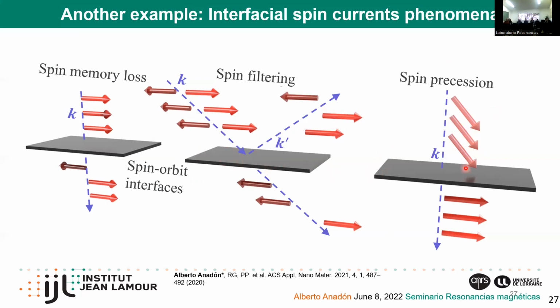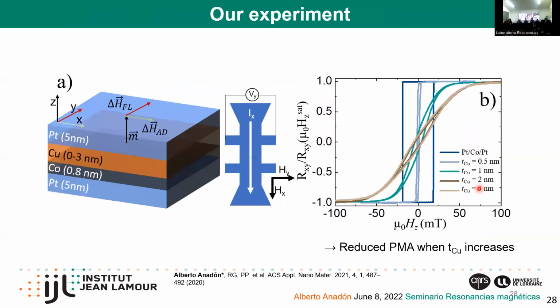But we can also have other effects like spin precession, for example, also able to change the spin polarization of our spin current. And to study these effects, we prepared stacks like this: platinum, cobalt, platinum, with a copper interlayer between 0 and 3 nanometers. And in here, our plan was to study what's the effect of the interfaces in copper in this system.